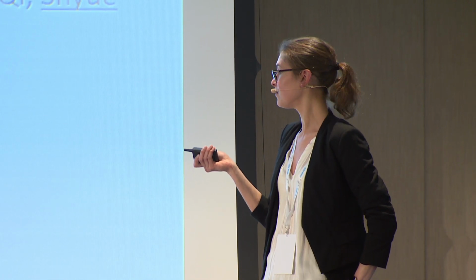So a lot of, as we now see in the battery field, a lot of interesting materials are ball milled to create interesting compounds. So this is obviously a challenge because it's not a scalable method. Do you see any ways to make these high defect structures, maybe in other ways? So some of them, yes. These ones, I'm not sure. We haven't really tried that for those chloride systems. For the disordered rock salts, we've shown that they can be made by microwave, which might be more scalable, and clearly it's of industrial interest to scale. But for the chlorides, we haven't really tried anything else so far.